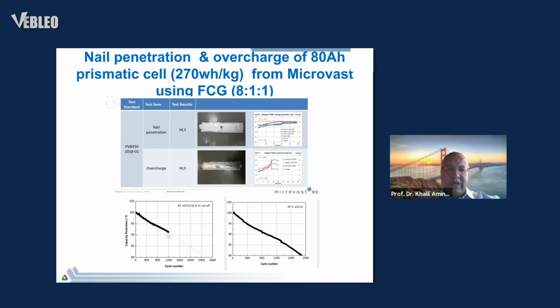So actually the expectation is they will get 3,000 cycles at room temperature. Now the requirement for electric vehicle cycle life is only 1,000. Even at high temperature, they can achieve 2,000 cycles. So this is a very, very impressive result.